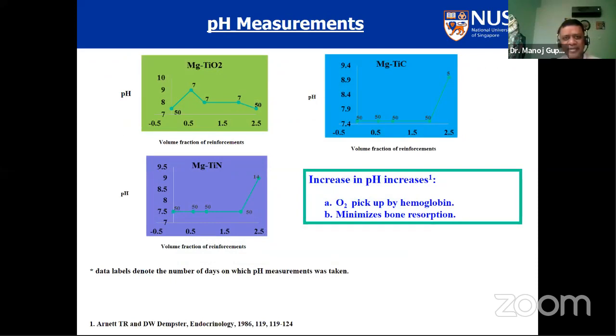When you do corrosion testing in the physiological medium, the pH changes. When the pH change is high, that means the corrosion is high. So when you choose a reinforcement, you have to choose the best one. In this graph, for example, you see magnesium TiO2 in the top left corner, and at 2.5% for 50 days, the pH fluctuation is very small. So if I have to go for the MgTiO2 system, I'll go with 2.5% TiO2.